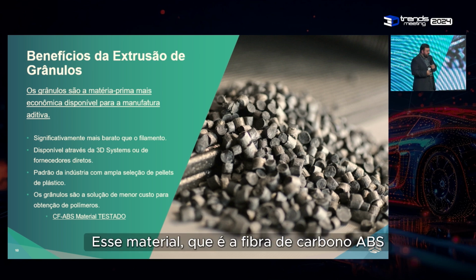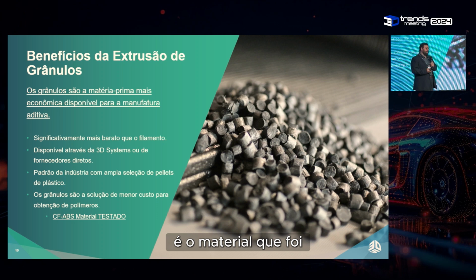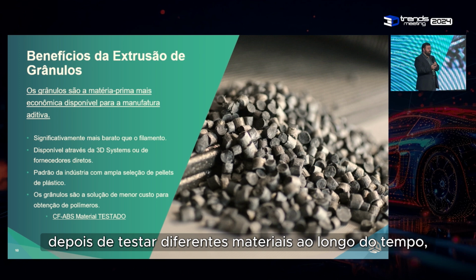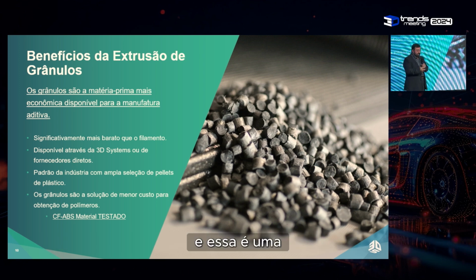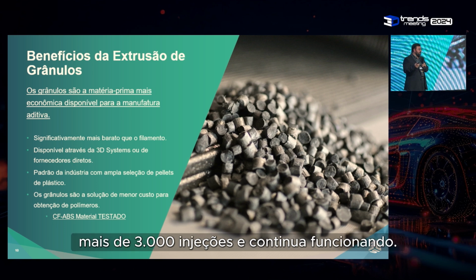This material, the carbon fiber ABS, is the material that has been proven in the last 3 years after testing different materials through time. And this is a good solution that has been lasting more than 3,000 shots and still working.